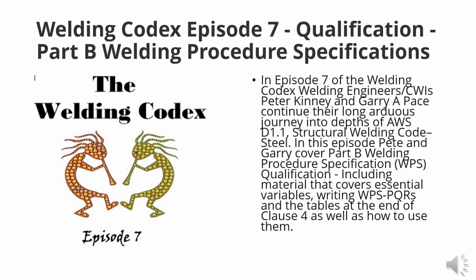So for like gas metal arc and flux core, you've got listed here, is that a CC or a CV machine? You need to address that. If it's not on there, you need to address it. So how did we do this? Were we using constant voltage or constant current? It needs to be addressed because the deposition of the weld metal is going to be drastically different depending on what output you have, constant voltage or constant current.